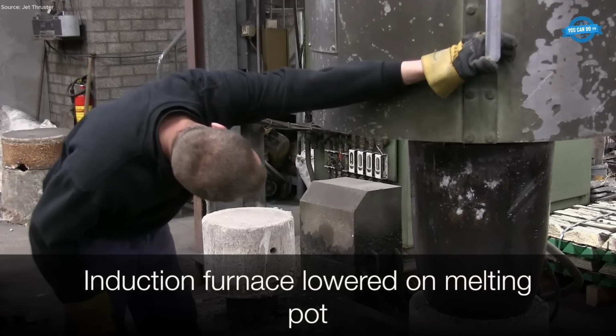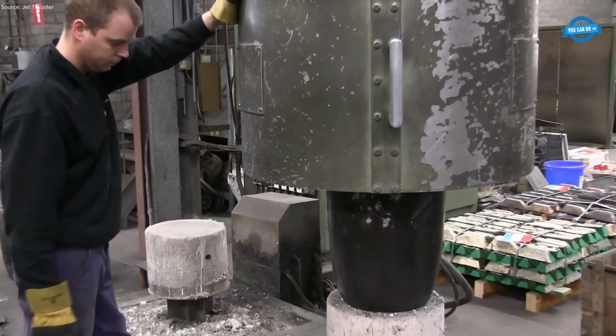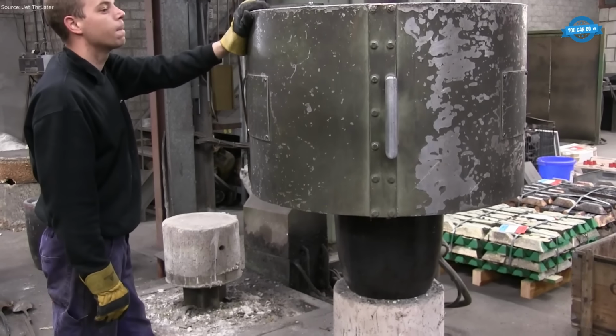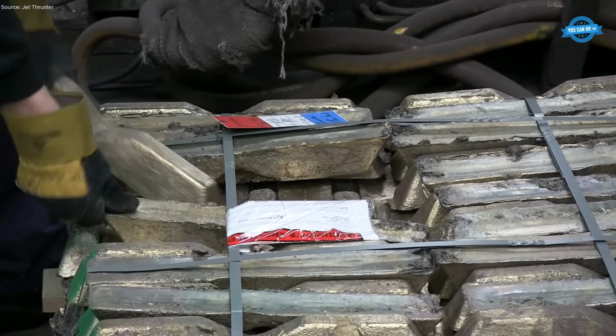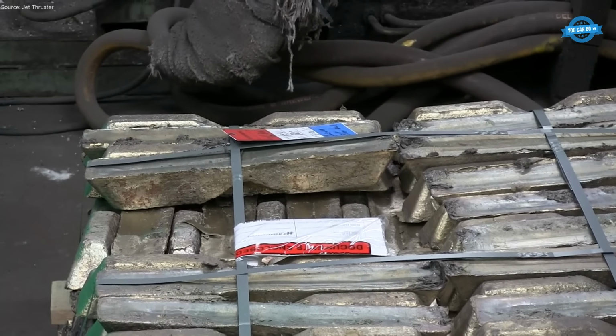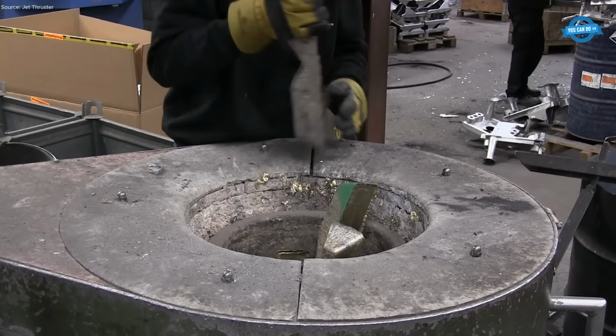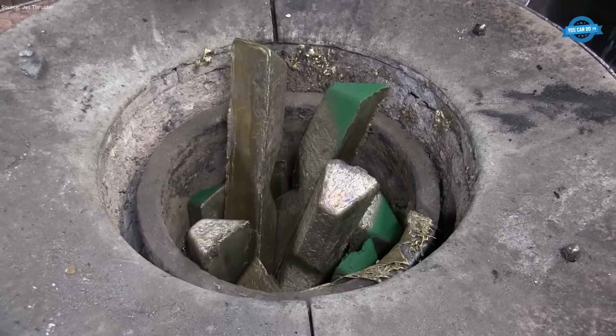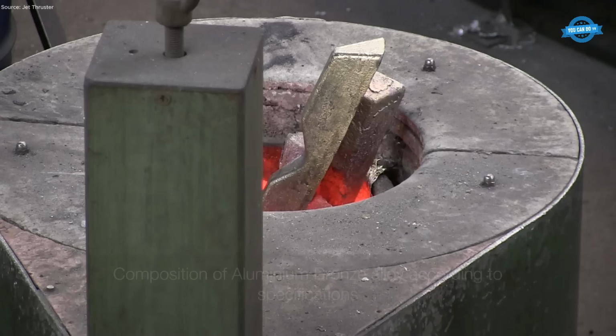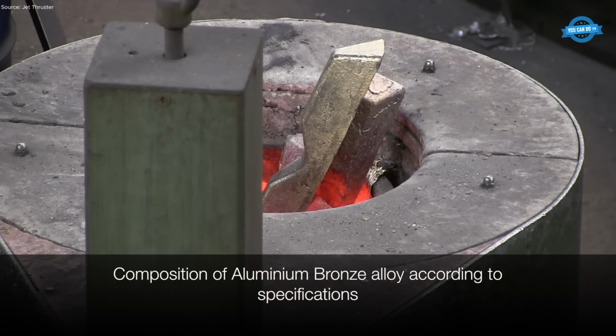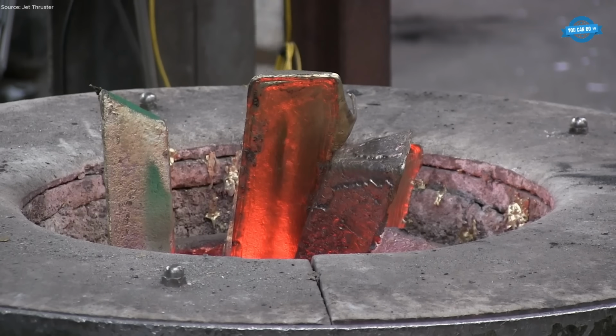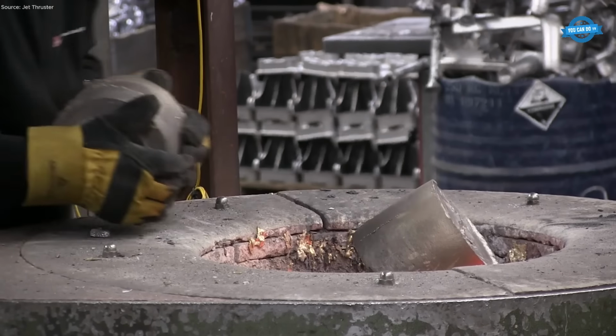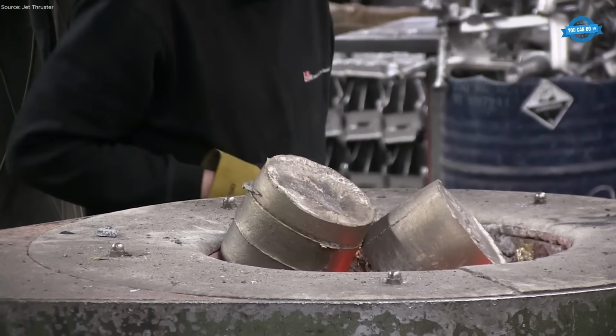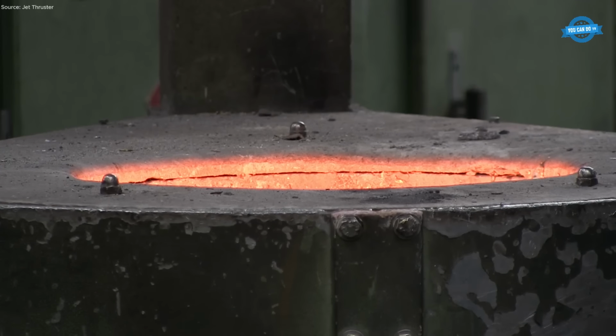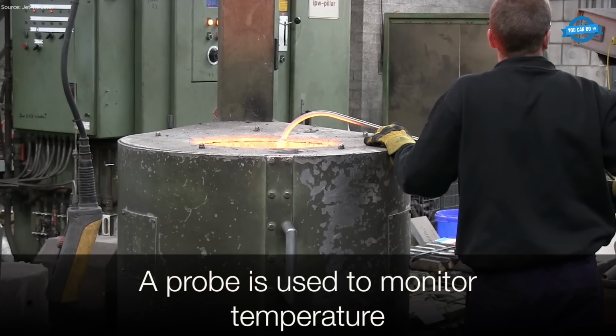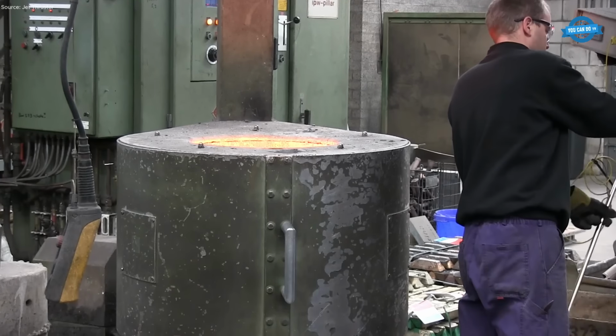Meanwhile, the alloy preparation begins in an induction furnace, which is lowered onto a melting pot containing raw materials. For the jet thruster impeller, an aluminium-bronze alloy is used. This material is selected for its high strength, wear resistance, and superior corrosion resistance in seawater environments. The alloy composition is carefully controlled to meet exact specifications. Temperature is monitored continuously using precision probes, ensuring optimal casting conditions. As the metal melts, impurities and slag are skimmed off to maintain metallurgical purity.